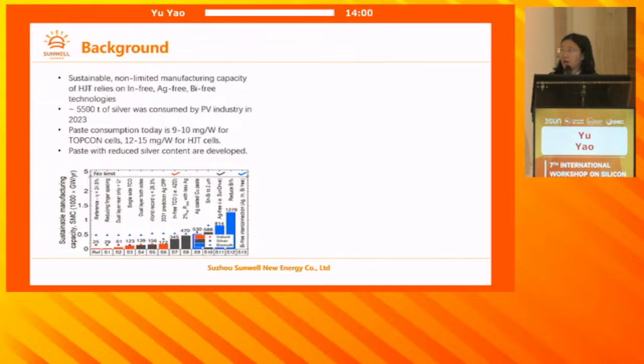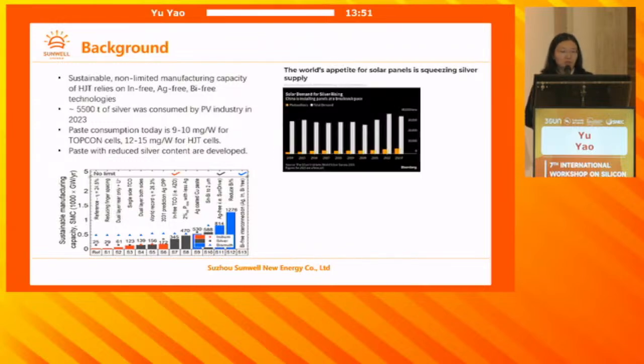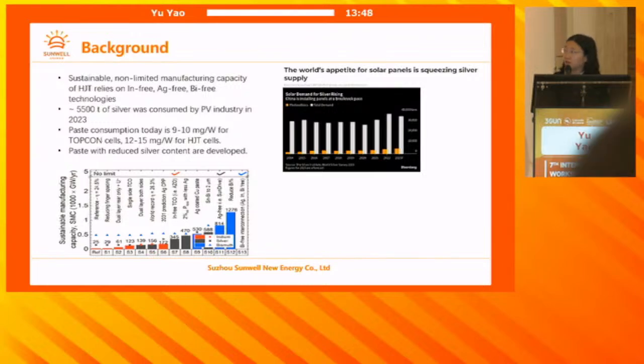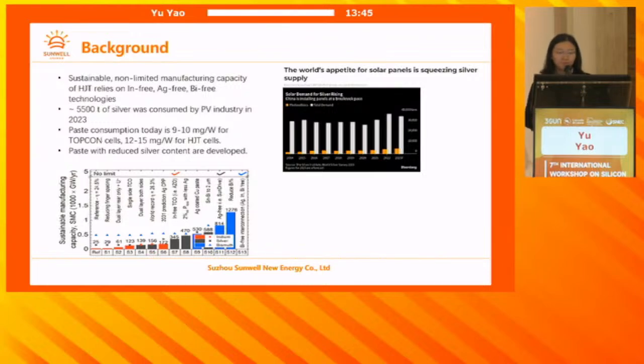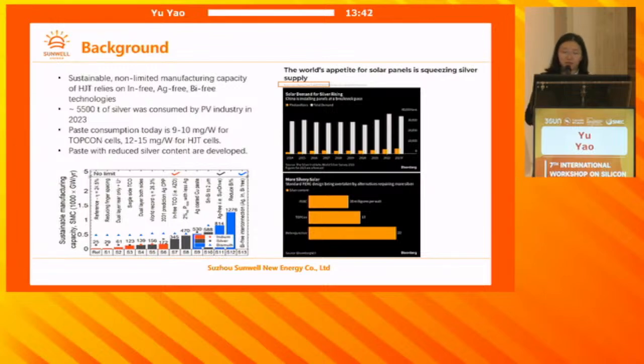And today we are able to say that we have a solution ready, industrial scale for silver-free. You can see from this Bloomberg survey that there were 5,500 tons of silver used by the PV industry last year. Last year they were also claiming that for different technologies, this amount of silver is needed. And we see from last year till now, the industry has done a lot of work to reduce that. Nowadays, it's 9 to 10 milligram for TOPCon and 12 to 15 milligram a watt for heterojunction cells. These are in terms of paste. And we know that there are pastes with reduced silver content, so we are doing better than the figures in the Bloomberg report.